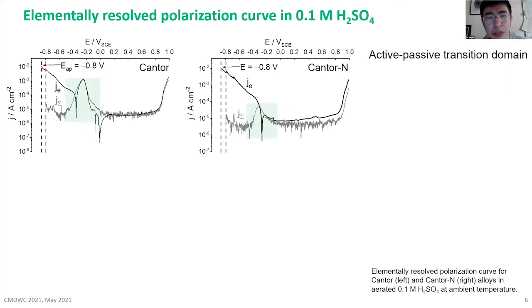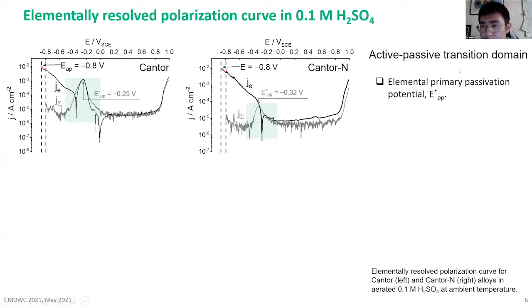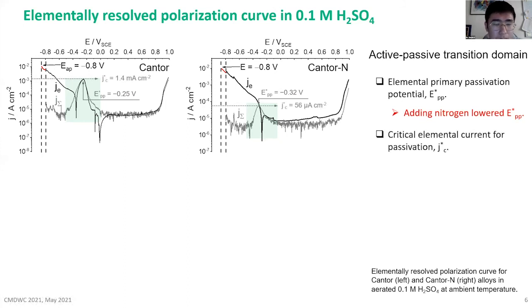And the most interesting part from this curve for us is the active-passive transition potential domain, highlighted by the green area. There are two parameters we can obtain from this curve. The first one is the elementally primary passivation potential. We can see adding nitrogen into this alloy lowered this potential for the Cantor alloy. And the next parameter is the critical current for passivation, which is the highest elemental current in the active-passive transition domain. We can see adding nitrogen lowered this current density for the Cantor alloy.